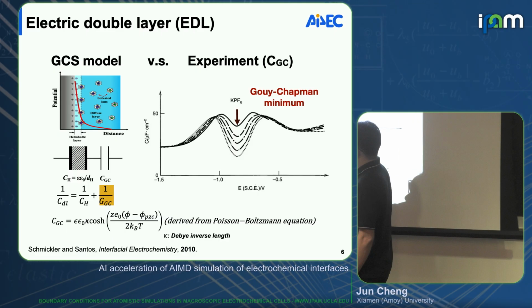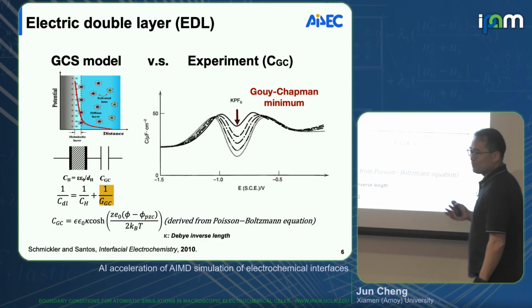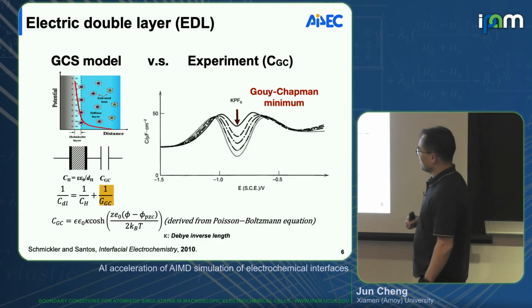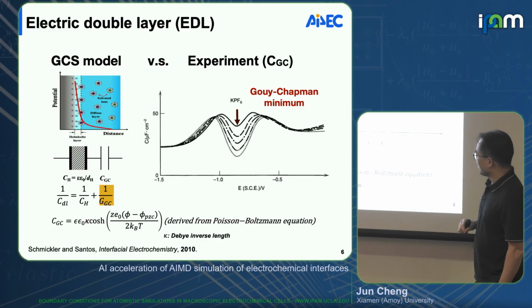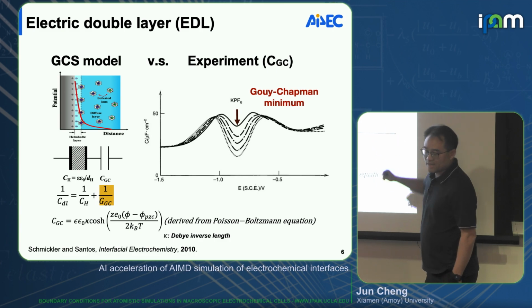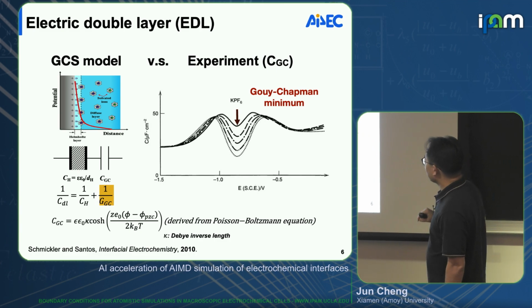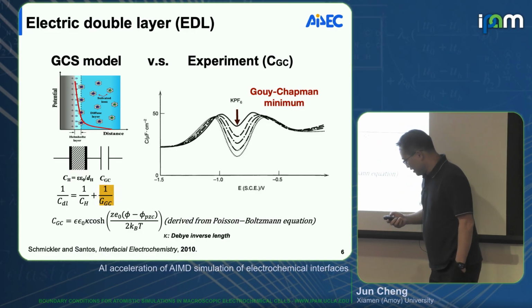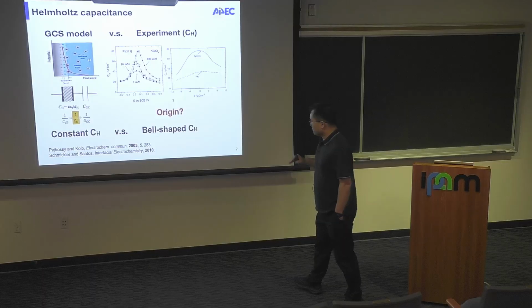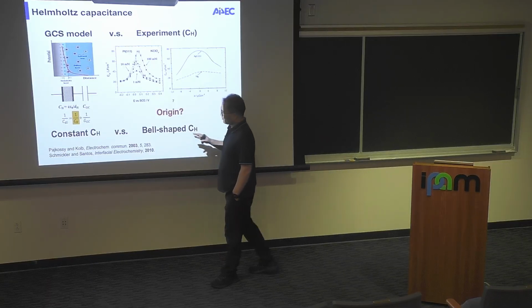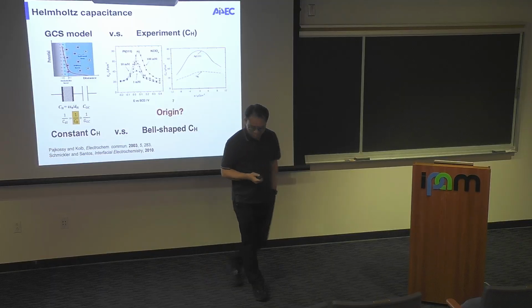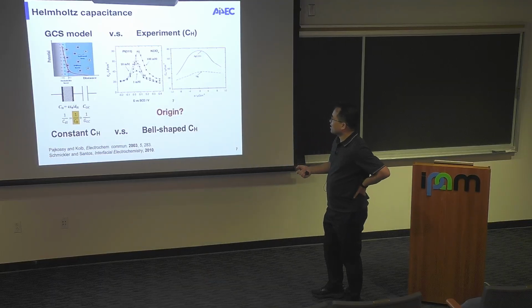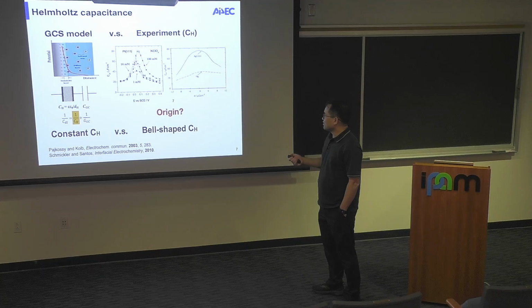So the model consists of two parts, this compact Helmholtz layer and this Gouy-Chapman-Stern, Gouy-Chapman diffuse layer. So this model accurately predicts this so-called Gouy-Chapman minimum in the dilute limit. For ab initio molecular dynamics simulation, we want to focus on this compact Helmholtz layer. Just to point out that in the traditional model, the Helmholtz layer is treated as a two-plate capacitor, where the capacitance is constant against potential, but it's really not the case.